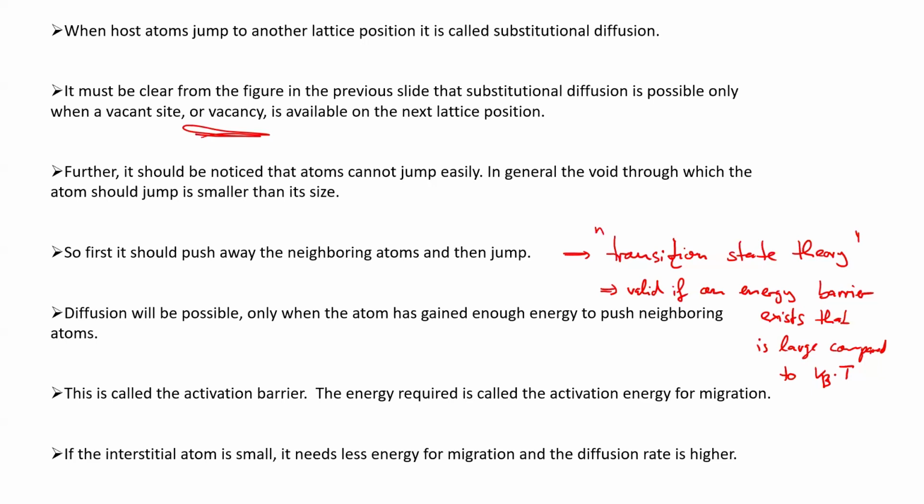If the energy barrier is sufficiently high, then the normal motion will not be sufficient to overcome it, because kBT is not enough on average to go above the barrier. That means you have to have a rare excursion, a rare event. And in statistics, rare event statistics are used to describe these processes.